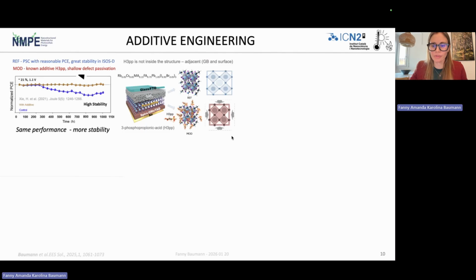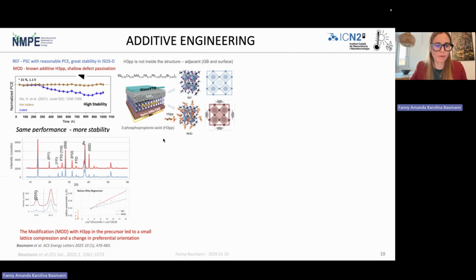The barrier that we're going to use in these experiments is a combination of, first, additive engineering inside the perovskite layer. For this we're using 3-phosphonopropionic acid, H3PP, that's added into the precursor solution, and this is from a previous work where we see that this modification with H3PP sits at grain boundaries and affects the preferential orientation, as well as induces a small compression in our devices. So we believe that it's part of the crystallization process, but it's not actively inside the structure of the perovskite.